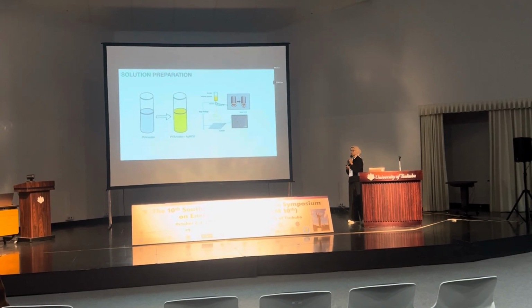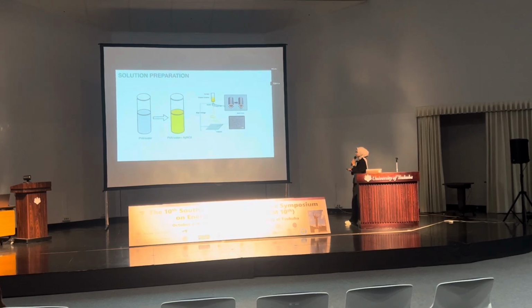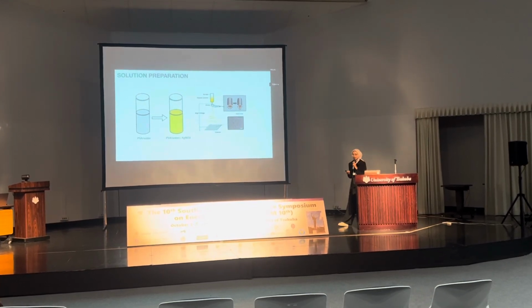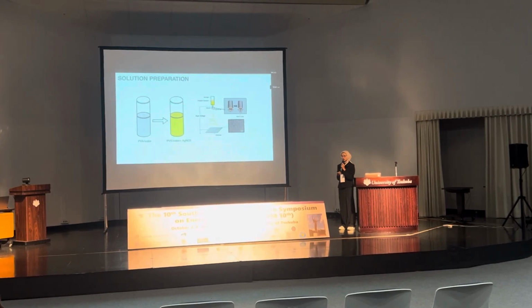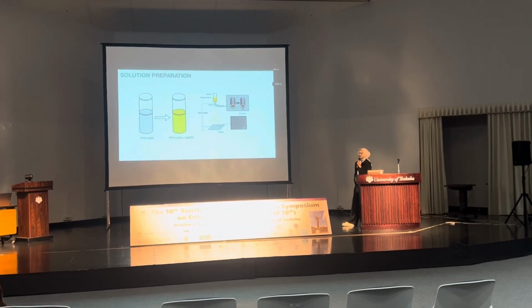After the PVA solution was prepared, I fabricated the PVA nanofiber by varying the spinning parameters, such as the feed rate, concentration of solution, the voltage, and the distance between the tip of the needle and collector. In addition, to expand the work, I added the antibacterial agent silver nitrate to create the antibacterial nanofiber with different concentrations of the antibacterial.